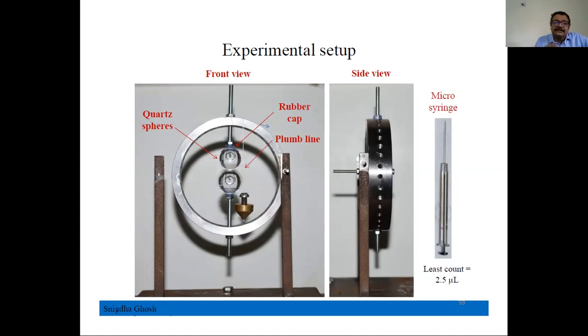You can do not only that, you can also change the orientation. You can rotate this and find out what the liquid amount will be in each orientation, and you can do these experiments. It's easy to do with water and glass balls or wax-coated balls. It is very difficult to do these experiments at high temperature using slag and graphite balls. It's much more difficult, but we can again use the techniques of mathematical modeling to see what will happen in the case of metal and slag.